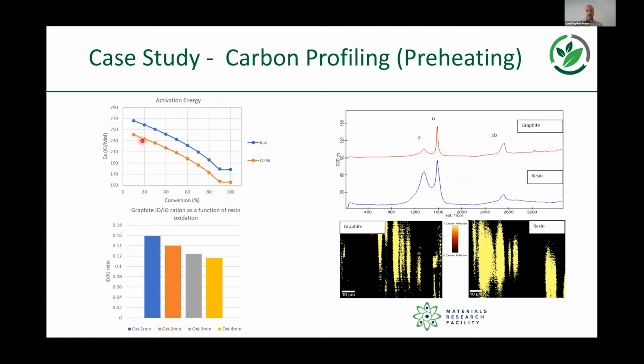But what we've noticed in the experiments that we've done is that they slide off quite quickly, and that's a function of the increasing levels of porosity that are generated as you degrade the material. So to try and understand what's controlling that degradation, we've entered into a nice collaboration via the Royce Institute with the Materials Research Facility at Culham. And what we've been using there is their in situ and ex situ Raman capabilities to look at how the degradation of the material changes as a function of this conversion.